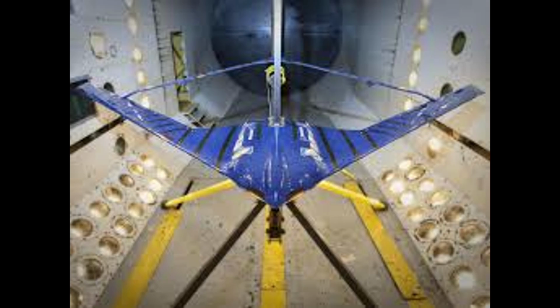Structural engineers overlay these aerodynamic findings with load histories. They calculate stress ranges at critical locations and compare them to original fatigue assumptions. The discrepancy is often stark. Components certified for a certain number of cycles were unknowingly subjected to far more damaging spectra. High angle of attack operations, once considered rare edge cases, had become routine. The structure did not fail prematurely. It failed exactly when physics said it would, given the loads it actually carried.